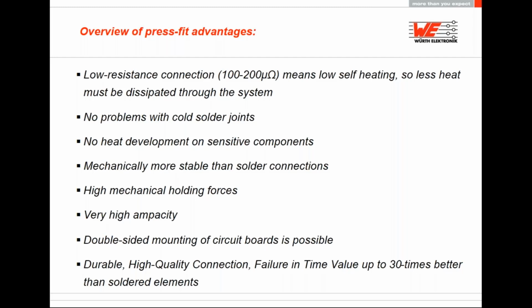So another thing is that it is mechanically more stable than solder connections. And as I said before, the metals are fused together and cold welding is stronger than the usual solder joint. Which also leads to high mechanical holding forces. So it is useful for tough environments where the connection might be subject to external forces. Also a very high ampacity, it can hold up to 300 amps, which is around 10 amps per pin.